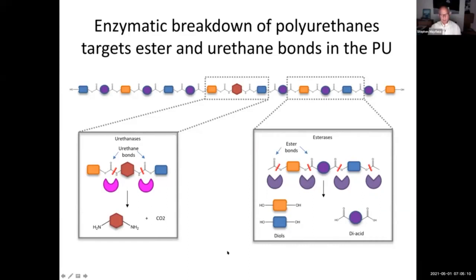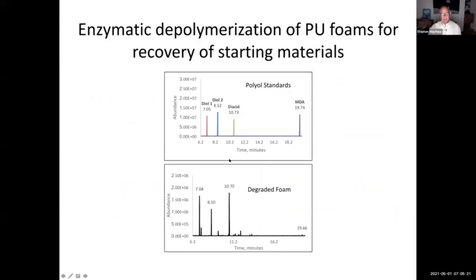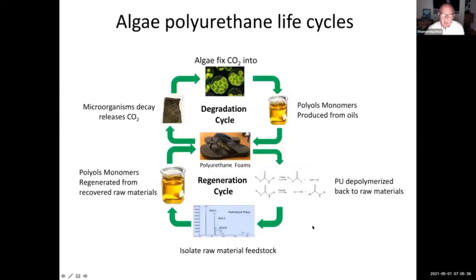Well, we looked at this and said, why don't we just take the enzymes and, rather than biodegrade these things, depolymerize them and see if we can recapture the monomers? So we did that, and this is a breakdown of a very simple foam, which simply had MDI, methylene diisocyanate, 2 diols, and 1 diacid. Sure enough, we could degrade those right back from the starting foam. So what does that give us an opportunity to do? We now have foams that meet commercial specification. If these things get lost, like you're out sailing and you lose your shoes and they end up in the ocean, they will naturally degrade.